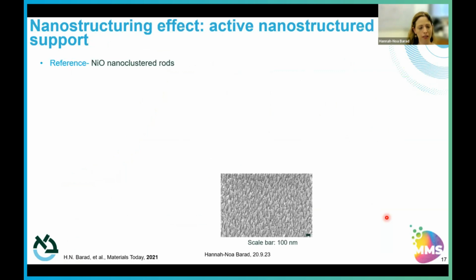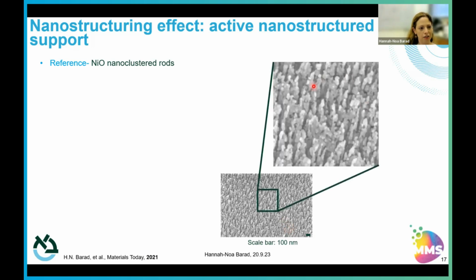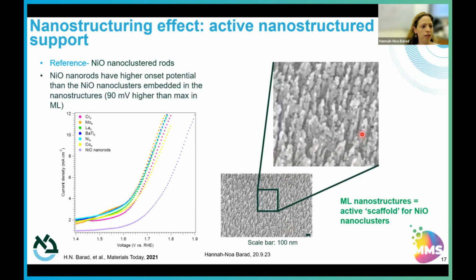So we made a reference library, and this reference library is composed of nickel oxide nano-clustered nanorods. They look pretty much like this. And you can immediately see that when we measure them, the onset potential for the nickel oxide nanorods, so this sample over here, is much higher, 90 millivolts higher, sorry, than our materials library.